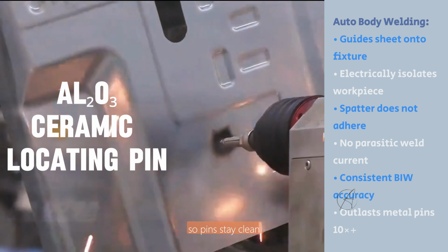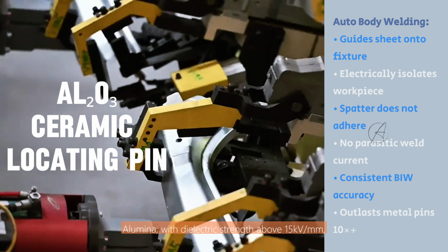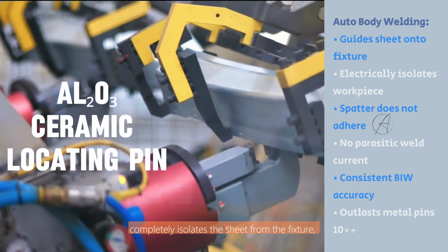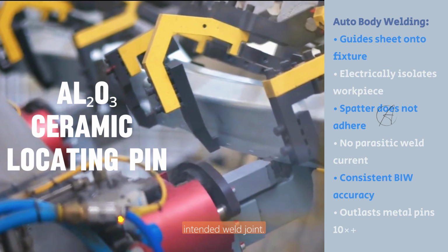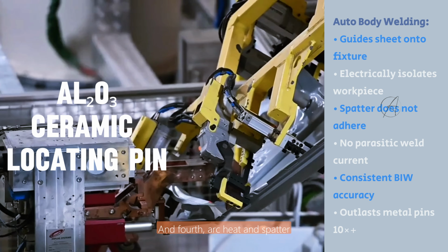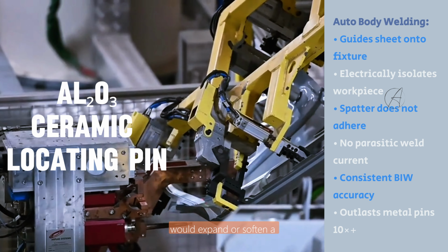Third, and most critically, a conductive metal pin creates a parasitic electrical path from the workpiece to the fixture body, diverting weld current away from the nugget and causing cold welds or inconsistent strength. Alumina, with dielectric strength above 15 kilovolts per millimeter, completely isolates the sheet from the fixture, forcing every ampere through the intended weld joint. And fourth, arc heat and spatter would expand or soften a metal pin over time, but alumina maintains dimensional stability up to 1600 degrees Celsius, holding fixture accuracy across hundreds of thousands of cycles.